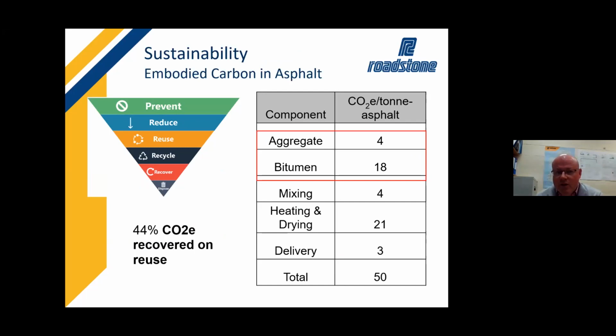Now, it's important to understand how you recover that, and that's through hot mix asphalt, because you're actually activating the bitumen, and so you're roughly recovering about 44% of the CO2 that was used. If people believe that by using reclaimed asphalt to build up road verges, that's recycling, really, all that you're even getting close to recovering is that 4 kg. You're not getting close to that. You're only making a saving of maybe 8% of that CO2 that could have been saved. It's a minute amount compared to what it is.